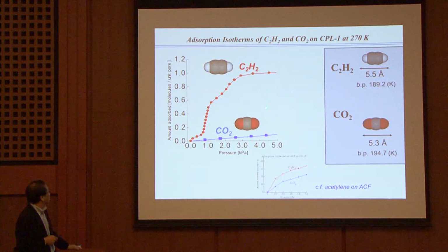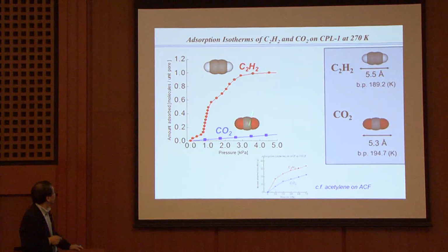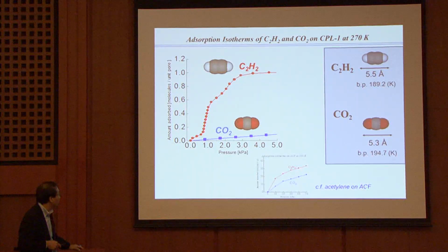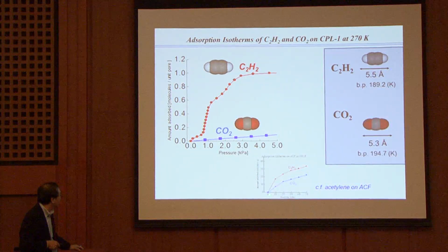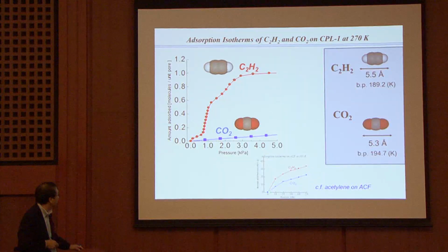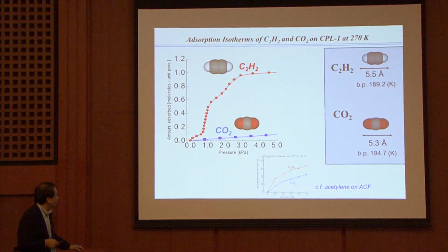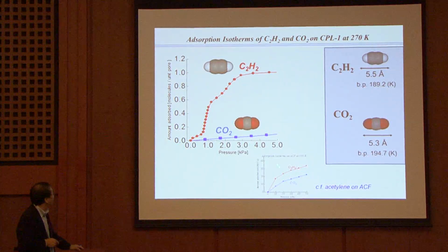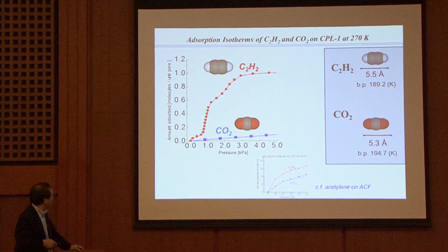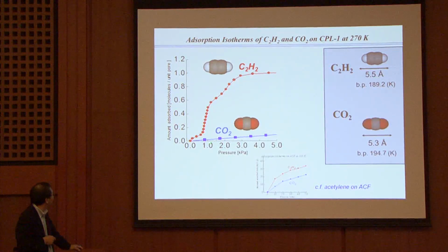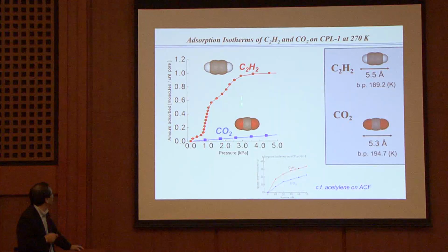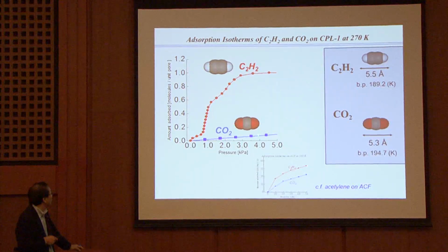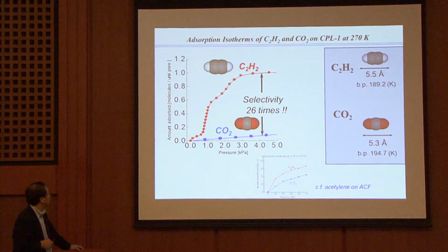And here, this shows this kind of sorption. But in the case of this, it is activated carbon materials. The CO2 and acetylene sorption profile is like this, pressure and adsorbed amount here. It is difficult to see the big difference, but our system is here. This case is high pressure, but this case is very, very low pressure. Already the acetylene is saturated in this case. What happens in this case?